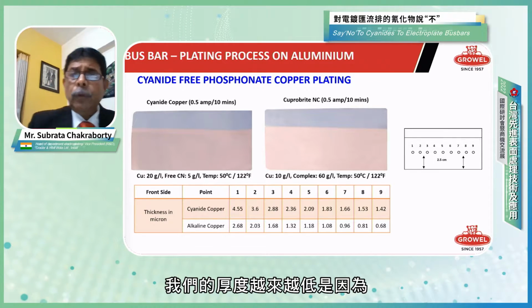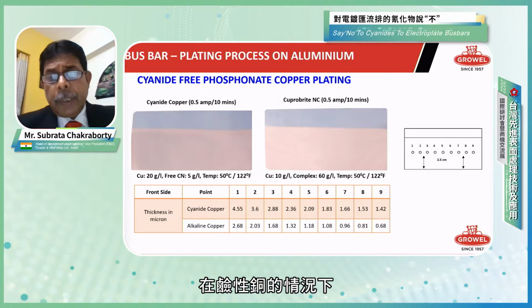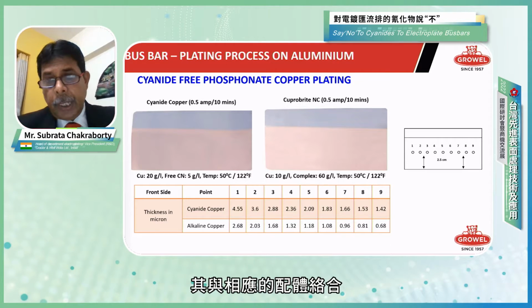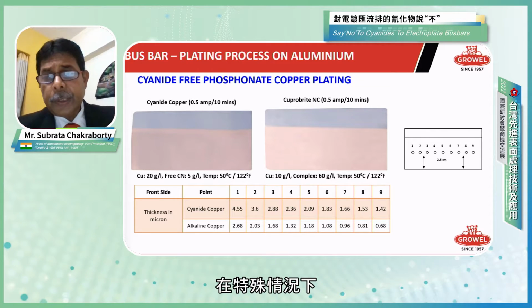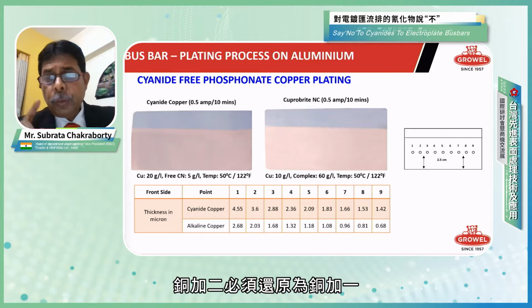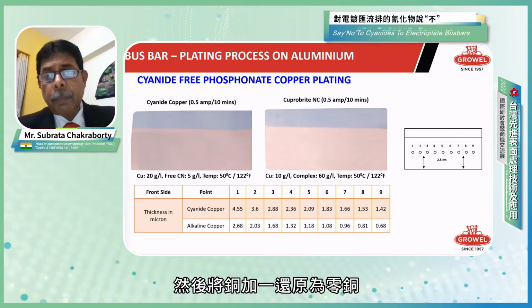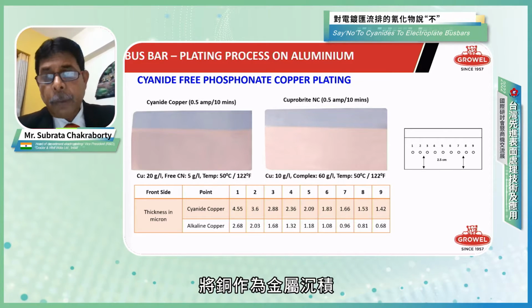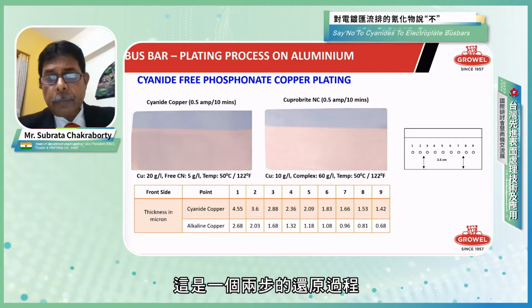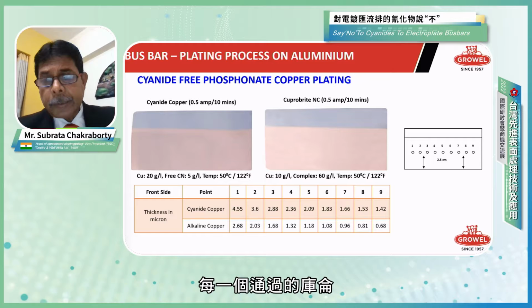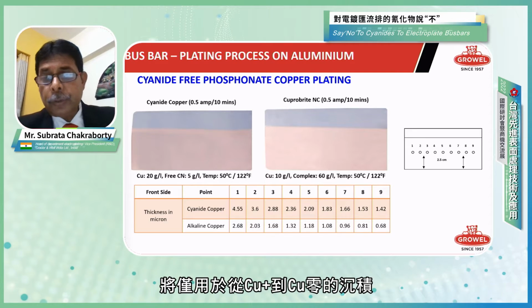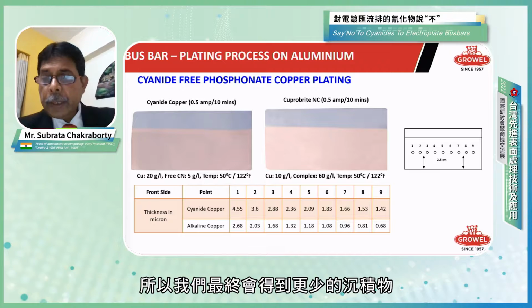Why we are getting lower thickness is that in case of alkaline copper, it remains in +2 stage, and it complexes with the corresponding ligand, in this particular case phosphonates and some organic carboxylic acids. During electrodeposition, copper +2 has to get reduced to copper +1, then copper +1 gets reduced to copper 0 to deposit copper as a metal. So there is a two-step reduction process. For each 1 coulomb passed, only about 0.5 coulomb will actually be used for deposition from Cu+ to Cu0, so we eventually get lesser deposition.